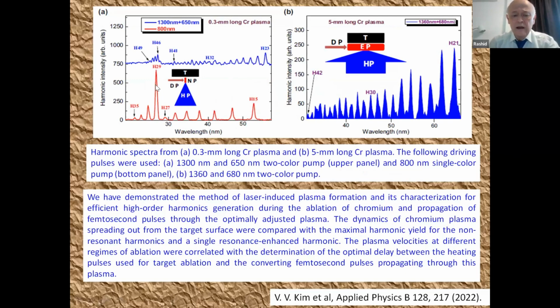we observed a strong resonance harmonic for the 29th harmonic, which significantly differs from the other low-order harmonics. This is unusual in the case of high-order harmonic generation, which commonly in gases shows a featureless plateau-like shape. In that case, we used a very narrow size of laser plasma, as well as 1300 nanometer radiation, which shows the same feature in the same spectral range, with some enhanced harmonic in the extreme ultraviolet range.